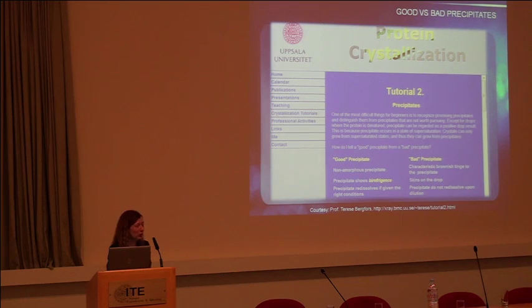For many years, people also got confused and thought that we could measure amorphous samples. And then I found this very nice website produced by Therese Bergfors. She's based in Uppsala in Sweden. It helps to separate the good from the bad precipitate. We both work with precipitates. The thing is that we cannot study amorphous precipitates. Therefore, she gives a very practical guide.